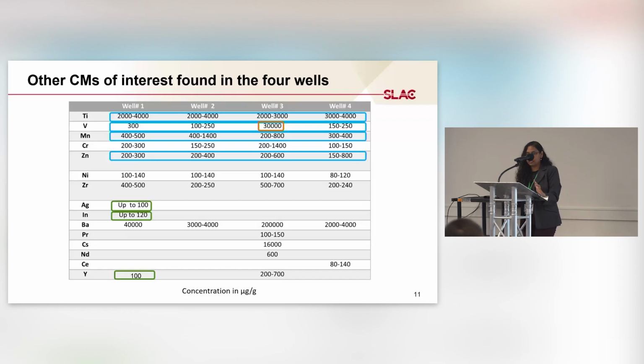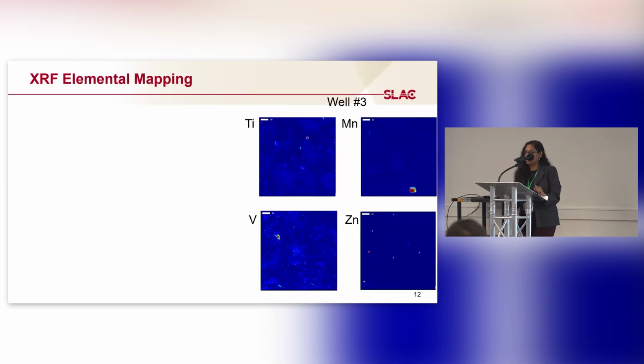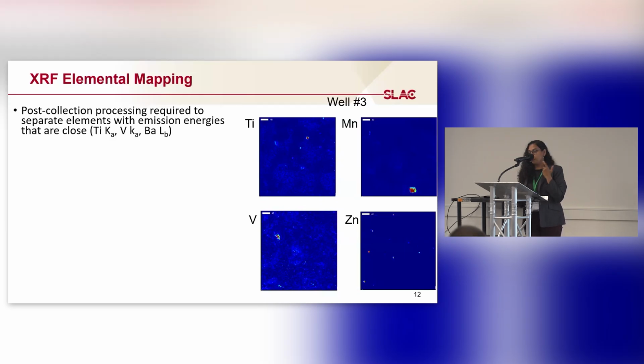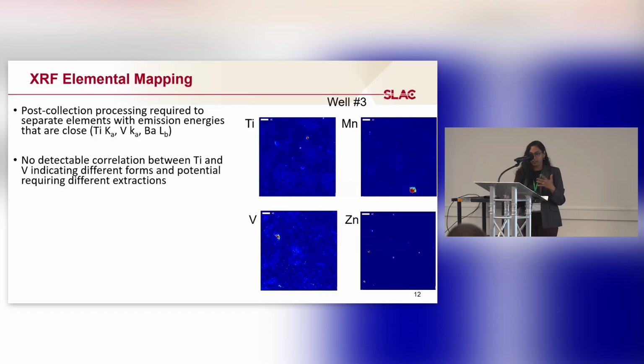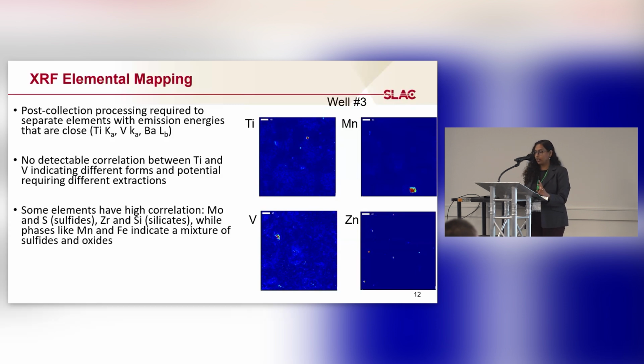So coming to the synchrotron-based analysis, X-ray fluorescence elemental mapping is a technique where you can do a mapping of the entire surface of your sample and see what elements are present in them. It can be useful with respect to elemental association, how they're associated and how they're distributed. Here we can see that the titanium and vanadium were not very correlated, so that would potentially require different extraction techniques. And some elements had high correlation, like molybdenum and sulfur were very much correlated, so possibly they exist as sulfides. Zirconium and silicon were correlated as well, so probably silicates.